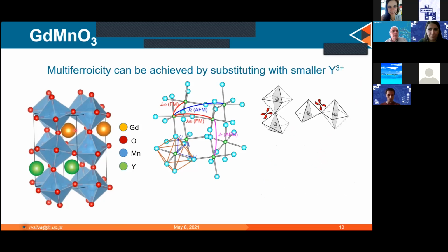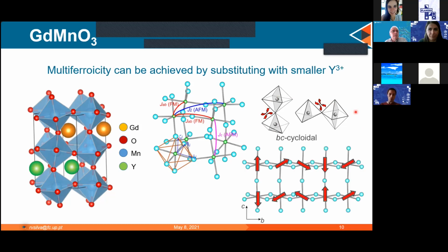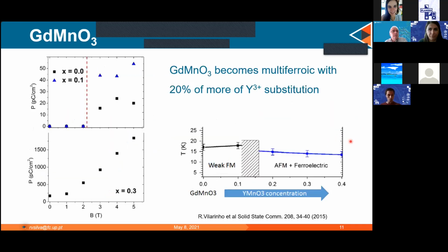We can now substitute some of this gadolinium by yttrium, and yttrium is smaller, and then you, on average, will increase these angles and obtain the same angles that you have in terbium manganite. So you can take a material that is not multiferroic and make it multiferroic by substituting some atoms. And showing the results for this, you obtain this cycloidal again. So in gadolinium manganite, where X, the yttrium concentration, is 0, you have no ferroelectric polarization until you apply 3 Tesla, as I've said before. And if you have 10% of yttrium, nothing changes. But if you have 30% of yttrium, now you have ferroelectricity even without applying a magnetic field.